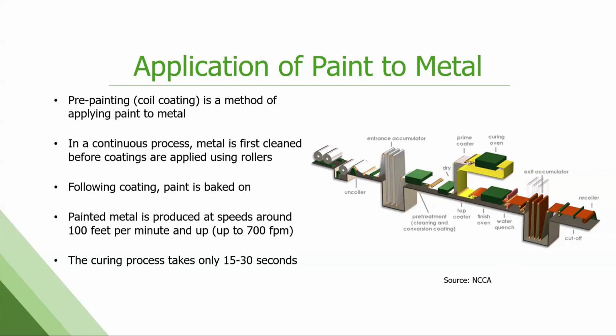Our lines here at Steelscape hold about 2,500 linear feet of metal from end to end. So they're quite large, usually multiple stories high as well. Those accumulator towers that you see there are anywhere from 4 to 8 stories high, depending on the size of the line. The speed is incredible, much, much faster than any other industrial coating to metal process that's out there.